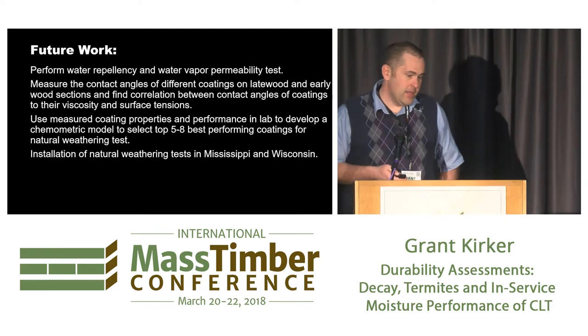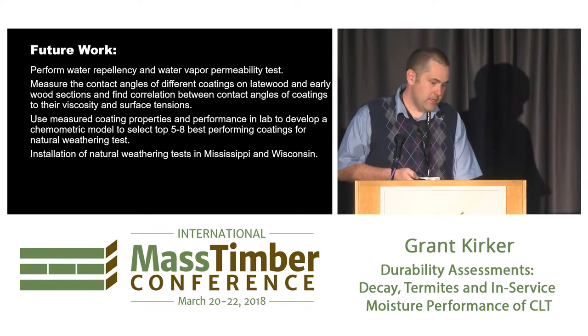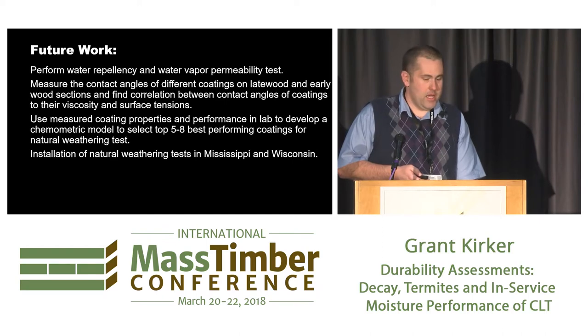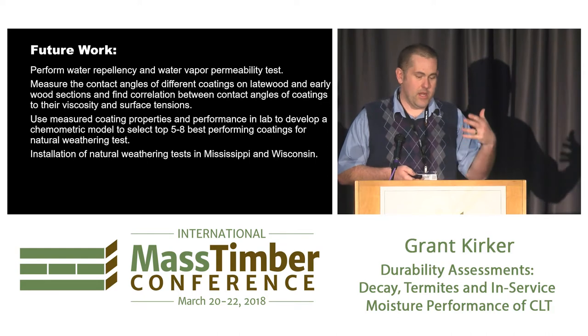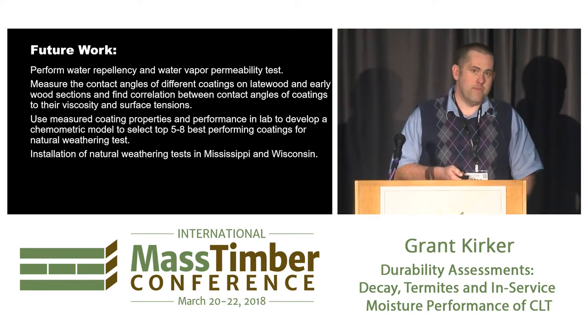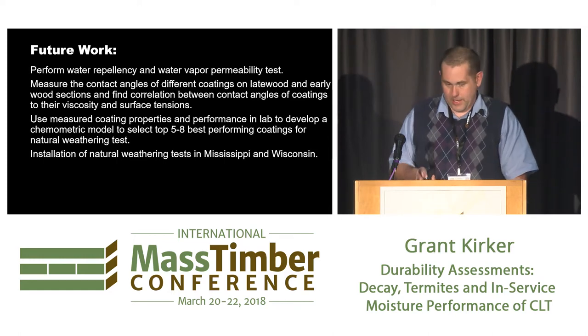So future work on this project, we want to look some more at water repellency and water vapor permeability tests. We're going to do contact angle measurements to look at how much beading is on the surface of these. And Mosgen is also working on developing some chemometric models so we can pare down some of these 38 and get locked into a final test group that we want to scale up for some field testing. These will be put on racks and exposed in Mississippi and Wisconsin.